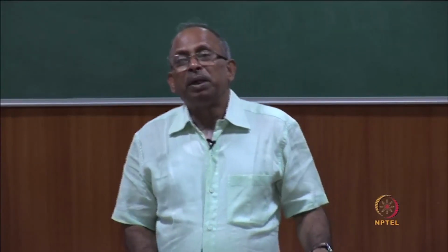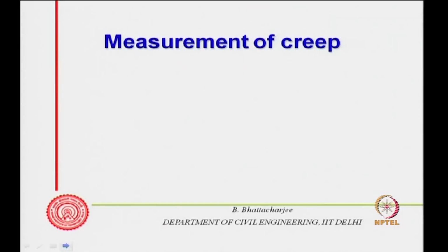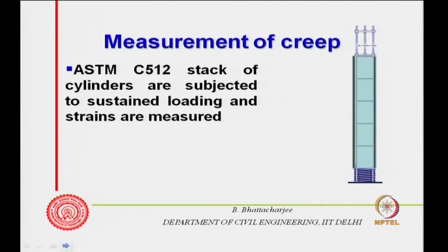So, that is related to prediction of creep, and now let us look into measurement of creep. The only standard perhaps available is ASTM C512, and what it suggests is that you stack 4-5 cylinders, subject them to sustained loading, and measure strains. It will look something like this: you have a loading frame, and that will have some sort of